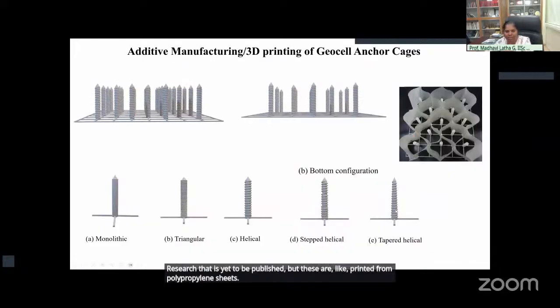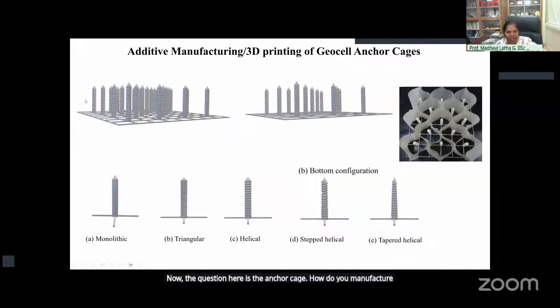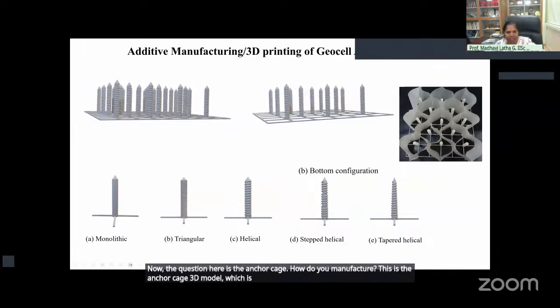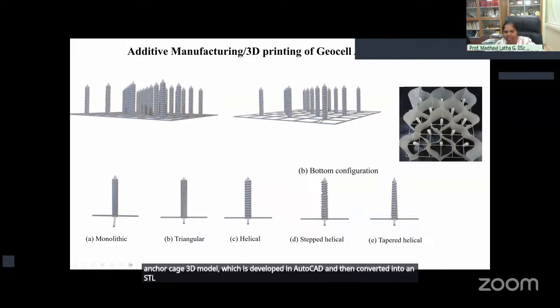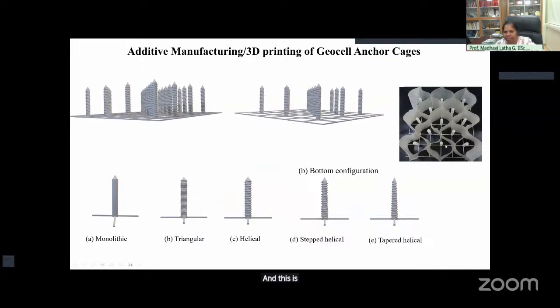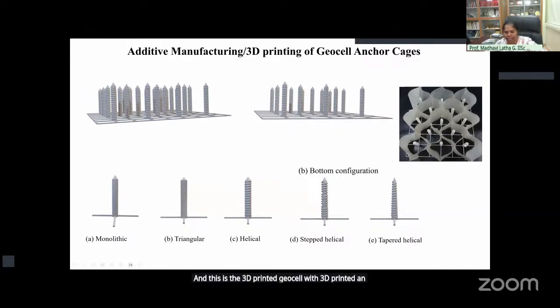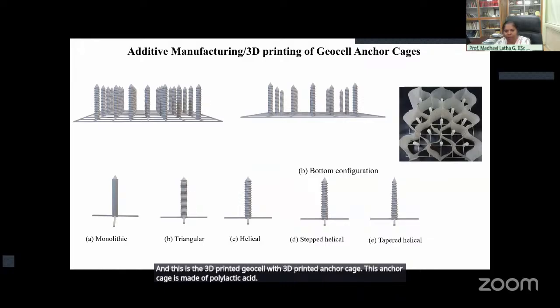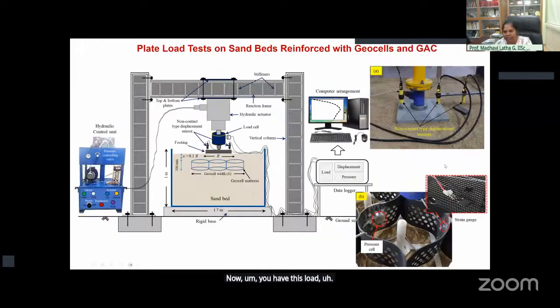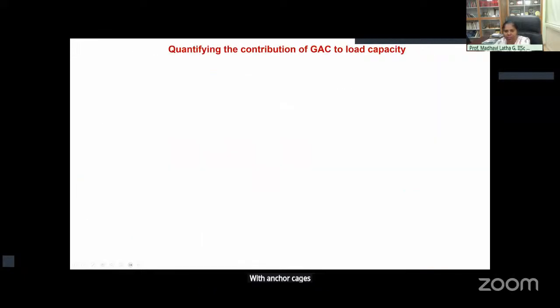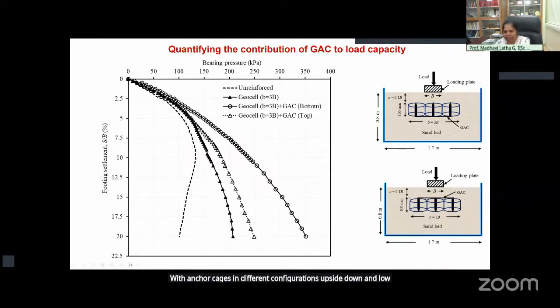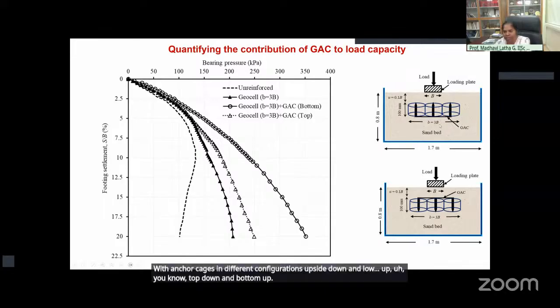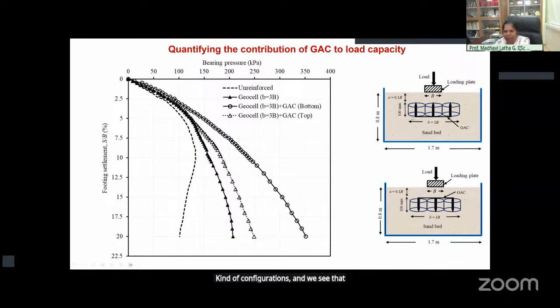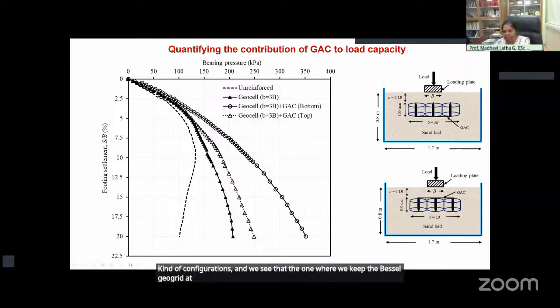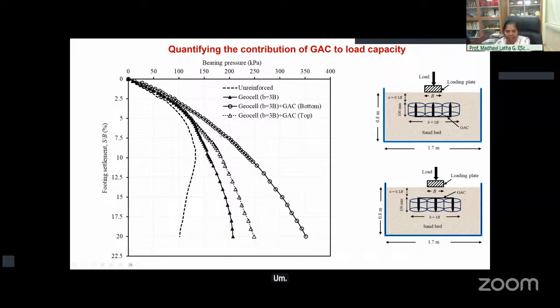Now the question here is the anchor cage. How do you manufacture it? This is the anchor cage 3D model, which is developed in AutoCAD and then converted into an STL file, which is needed for the 3D printing. And this is the 3D printed geocell with 3D printed anchor cage. This anchor cage is made of polylactic acid. Now, you have load tests on these geocells with anchor cages in different configurations, top down and bottom up. And we see that the one where we keep the basal geogrid at the bottom with the anchor pins facing upward gives you the maximum bearing capacity and reduced settlements.